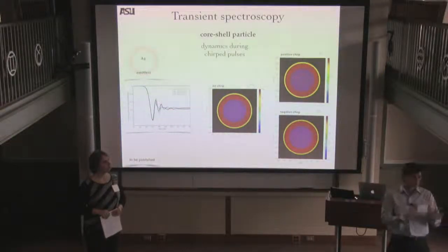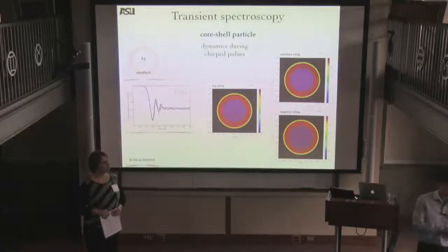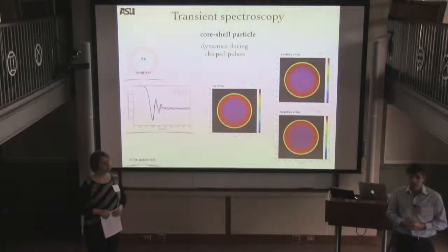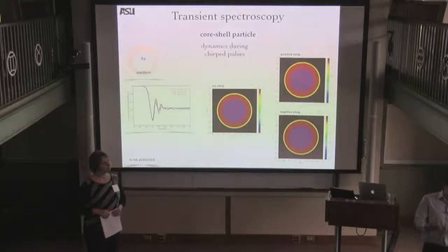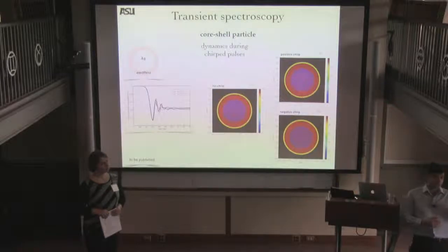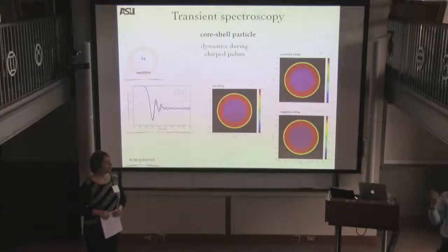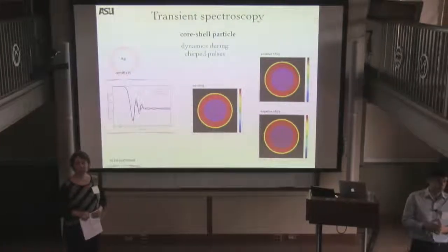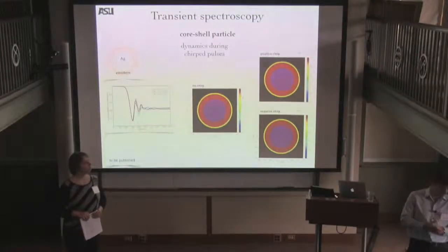So when you solve Maxwell's equations, irrespective of whether you include quantum effects or not, you have to include the correct dielectric constant for a dispersive material. Right? In this case, it's metal. Now, there are several ways. The easy way is to use a Drude model. In the Drude model, you have 3 parameters to fit. And this, of course, limits it to a certain frequency range where it's valid, right? Now, what we assume is that our dielectric constant for metal does not depend on intensity.